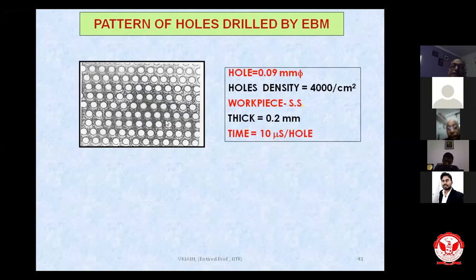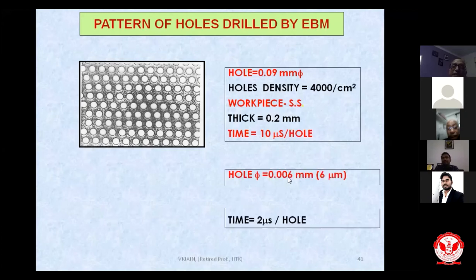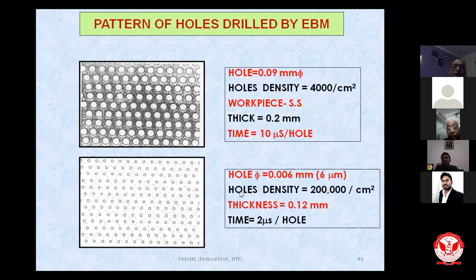But you know, industry people are not happy, especially the textile industries and fruit industries, which make the juice of the fruit. They say, oh, it is too big, we don't want that. Then they created holes of 6 micrometer, 0.006 millimeter. The hole density is 200,000 holes per square centimeter, the thickness is 0.12 millimeter, and the time taken is just 2 microseconds per hole. Here it was taking 10 microseconds per hole.